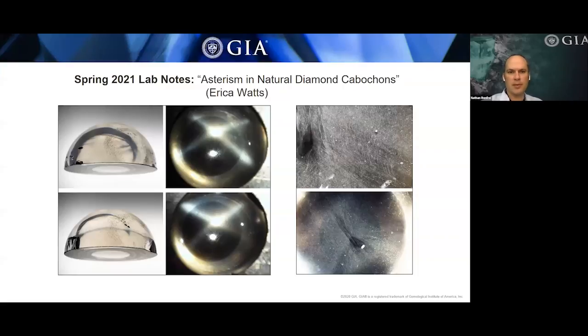But this diamond had a dense amount of these light scattering pinpoints that are oriented crystallographically with the host diamond. And so by cutting the stone into cabochon, or the pair of stones rather, these were each a little over 11 carats. And because of the inclusions, you actually have an asteriated diamond. So you have this 4-rayed star visible in these diamond cabochons, which is quite interesting. It's quite a novelty stone for sure.